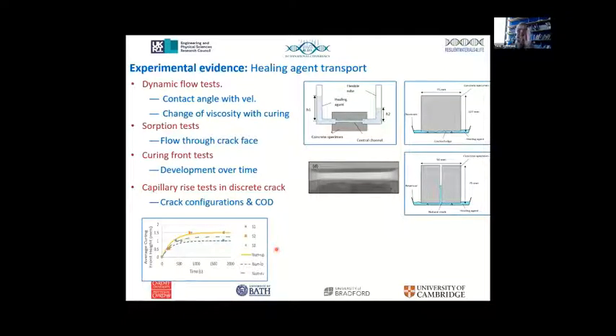If you've got a crack, it's full of healing agent, it doesn't all stay there. Some of it decides to migrate into the micro-cracked porous network around it. So we need to know how that works. So we did these sorption tests through a cracked face.